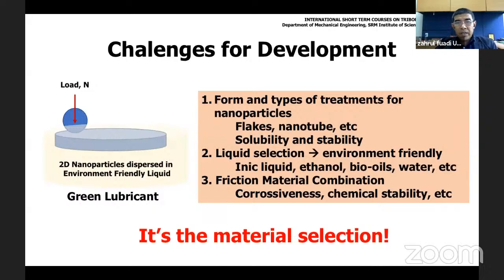and this liquid needs to be environment friendly, like for example the ionic liquid or ethanol or bio oil. Why don't we use water? Because the idea is to transfer the 2D nanoparticle to the contact interface. So the solution can be anything if it has good solubility and stability.